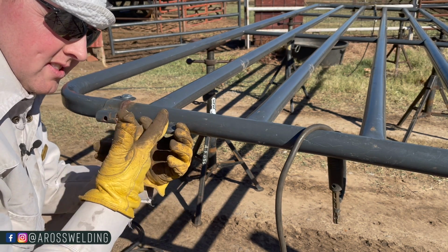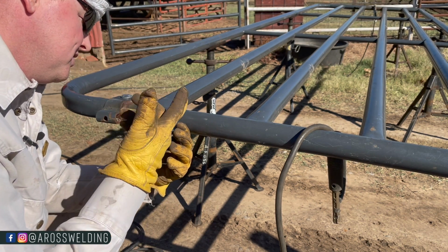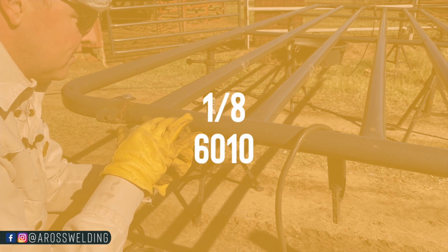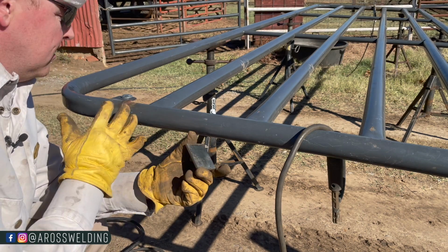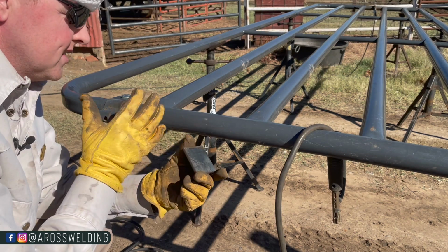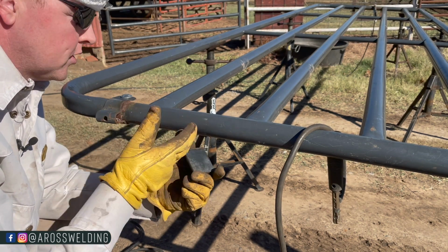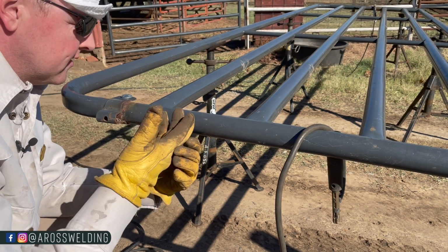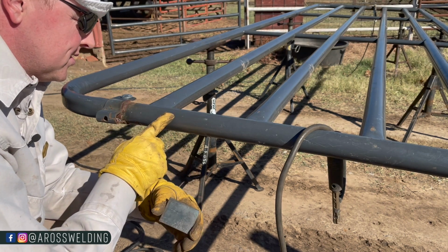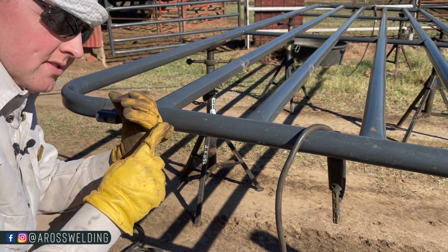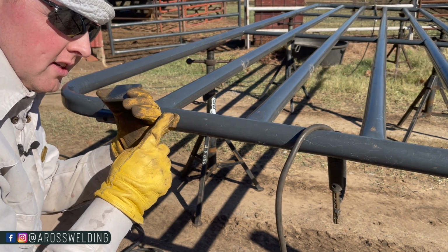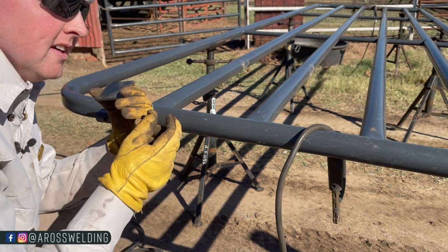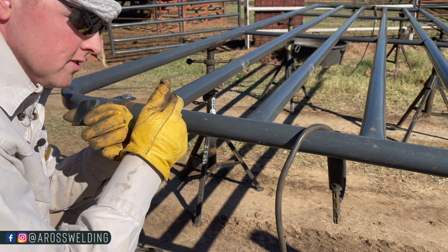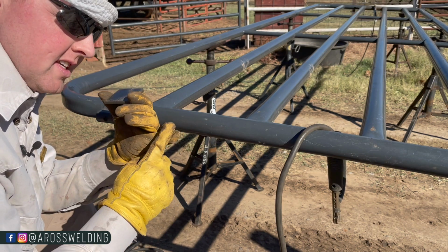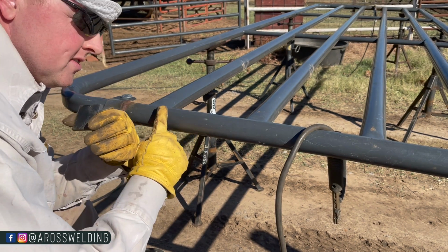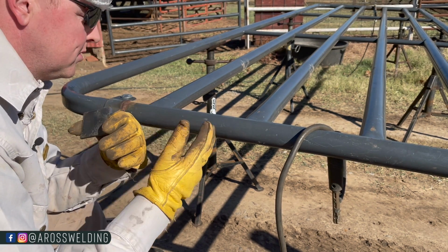And number two is the type of welding rod. I recommend using 1/8 6010. On something like this, generally speaking, on hinges on a gate, I recommend using 7018 because it's stronger structurally, less likely to crack, and a few other reasons. But with this thin material, 6010 for one is a little bit easier to weld, cooler versus like 7018. If you turn it down too much, sometimes it's harder to keep going. So 6010 is going to stay lit better for you. And on this thin material, it's going to be plenty strong enough.